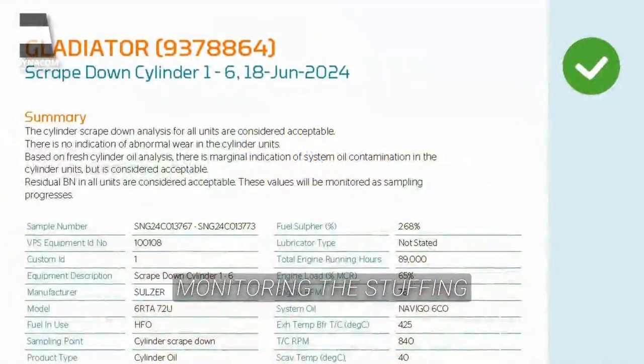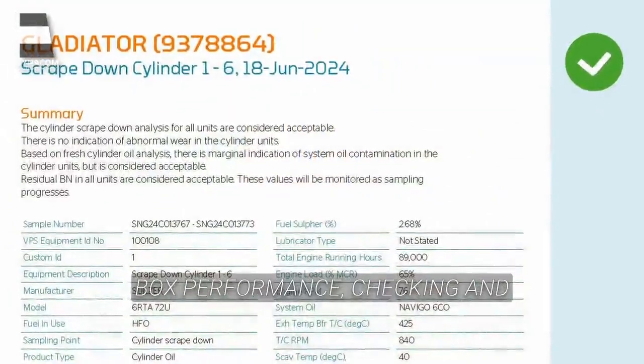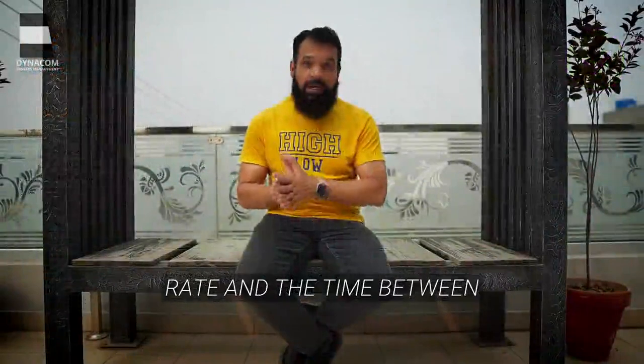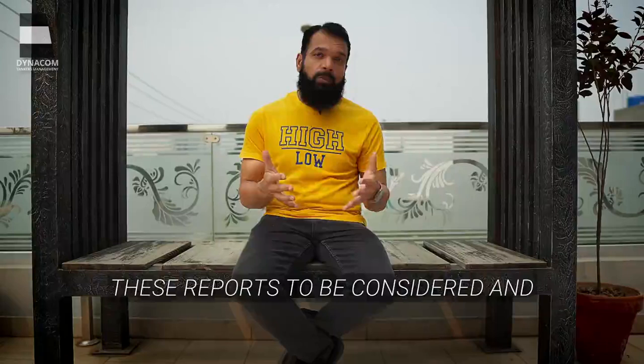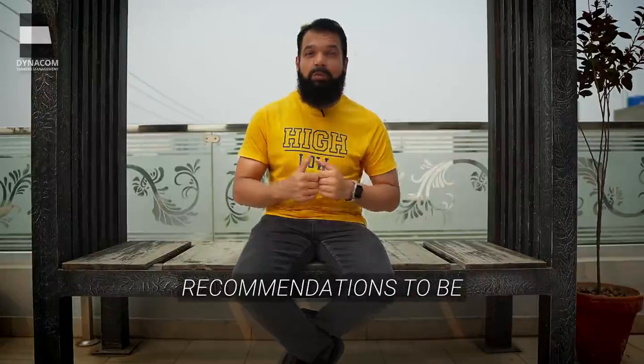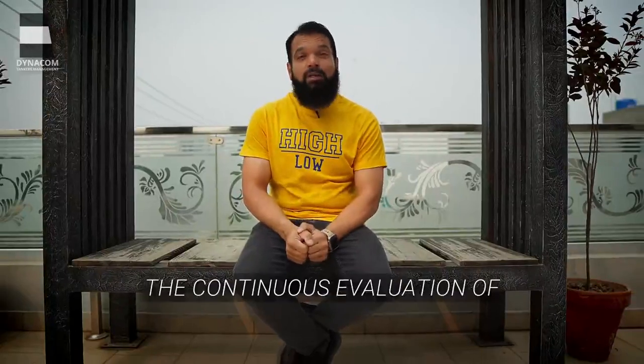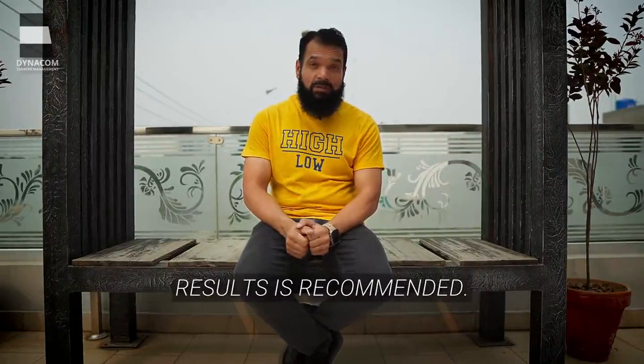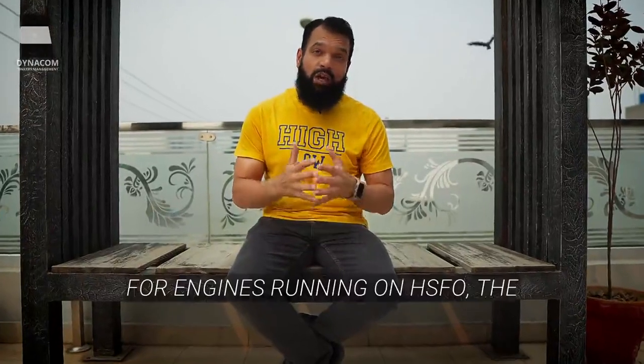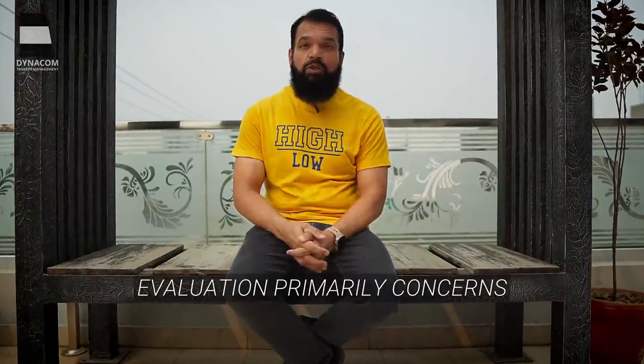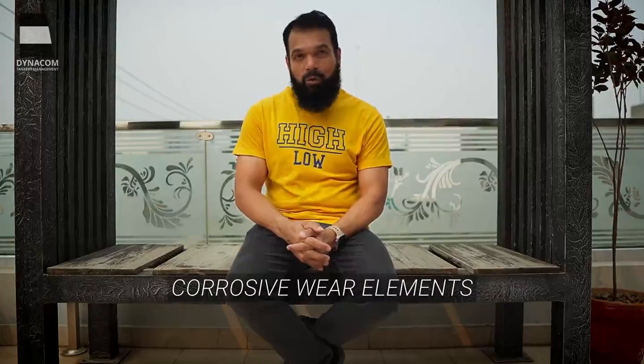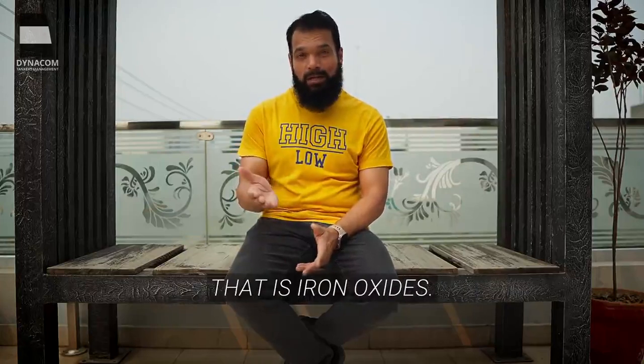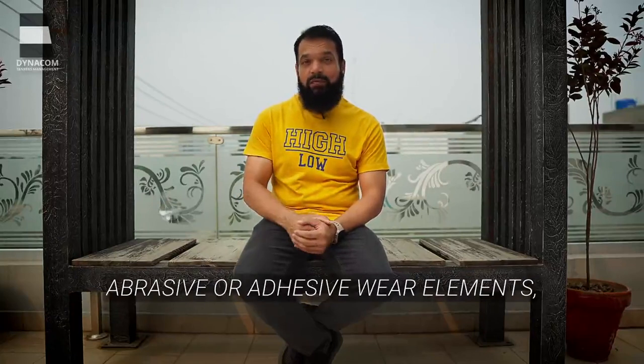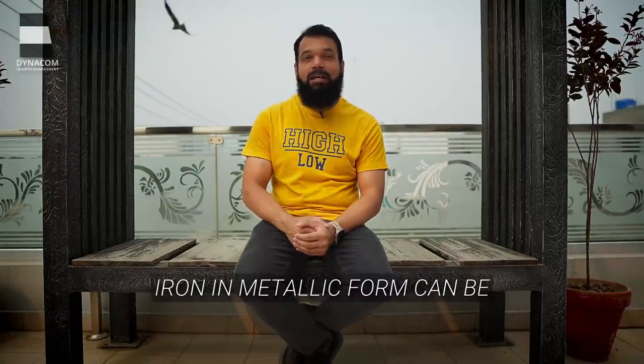Based on these results, the report gives us recommendations for monitoring the stuffing box performance, checking and optimizing the cylinder oil feed rate, and the time between overhauls. These reports are to be considered and recommendations implemented carefully. Continuous evaluation of scavenge drain oil analysis results is recommended. For engines running on HSFO, the evaluation primarily concerns corrosive wear elements, that is iron oxides, while for low sulfur fuels, abrasive or adhesive wear elements, iron in metallic form, can be expected.